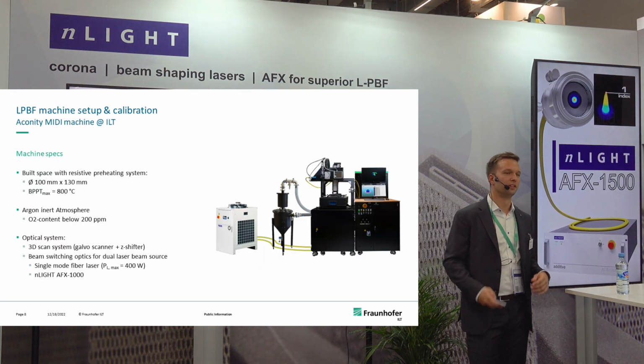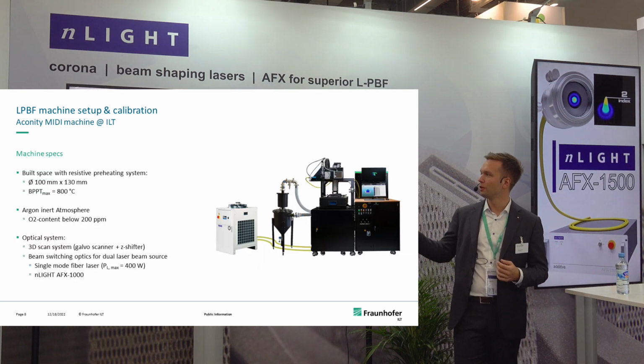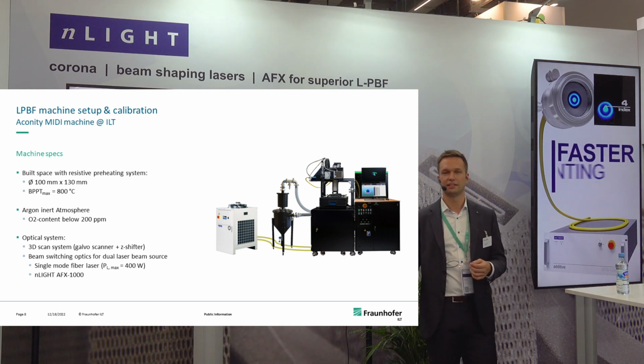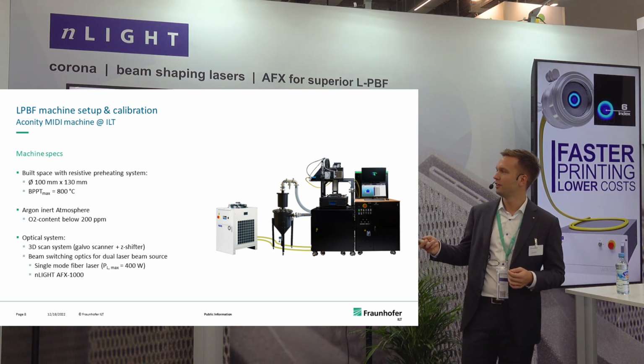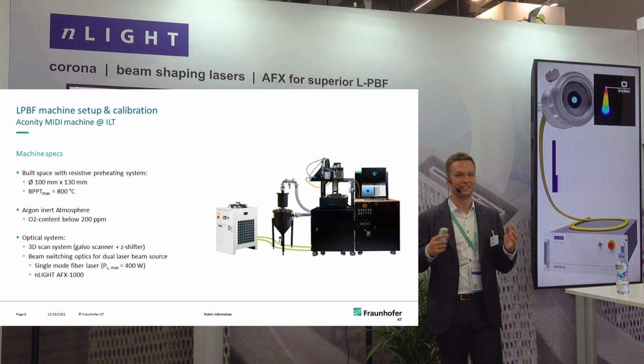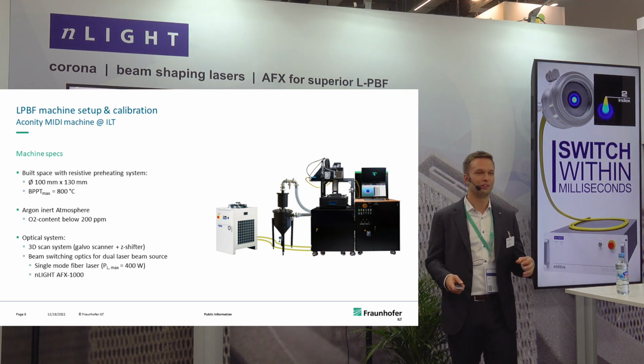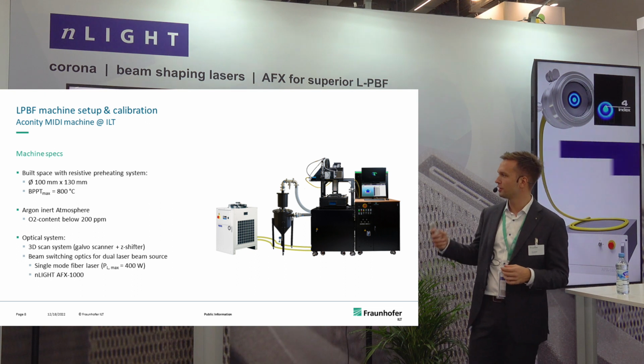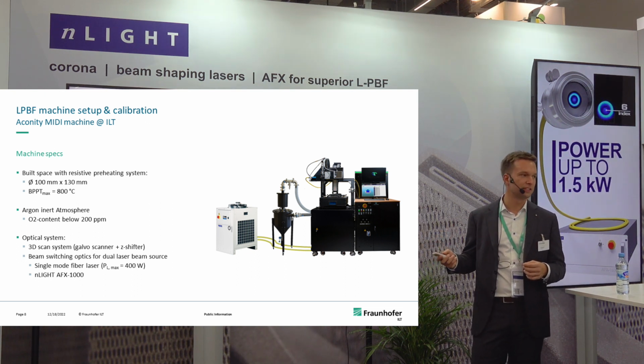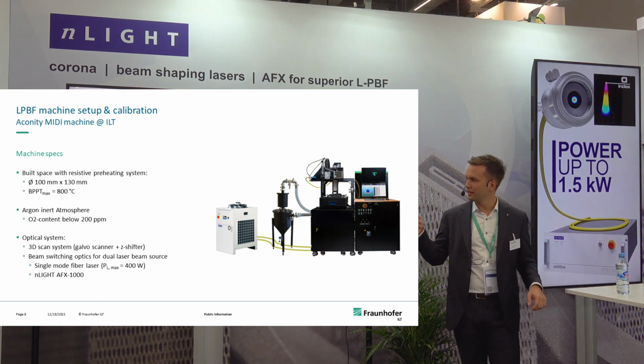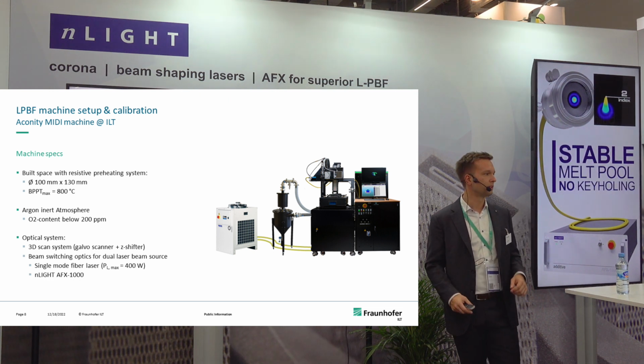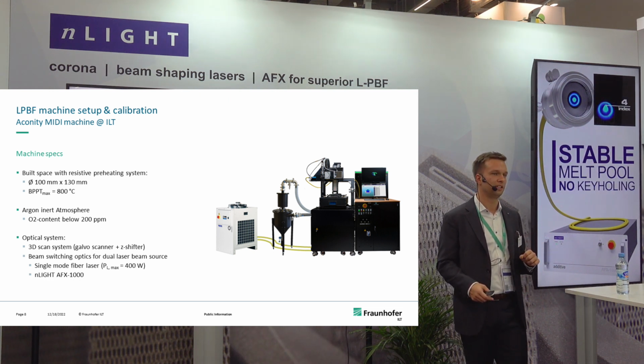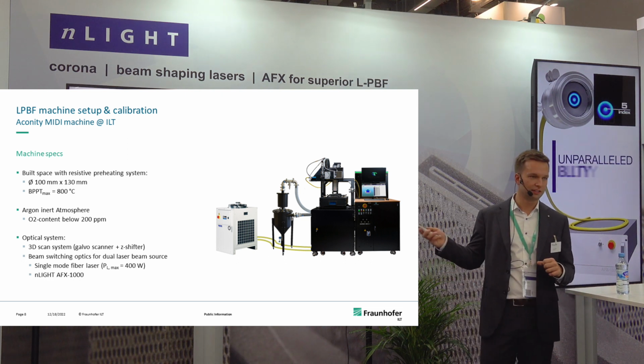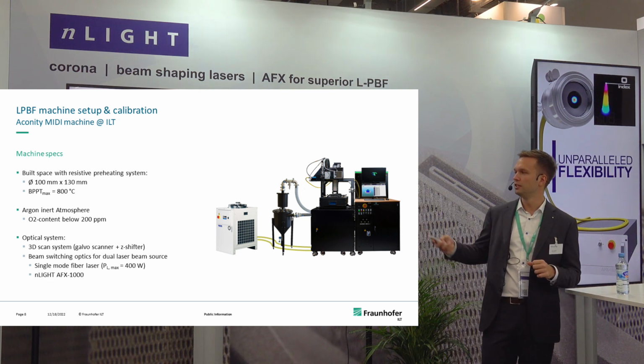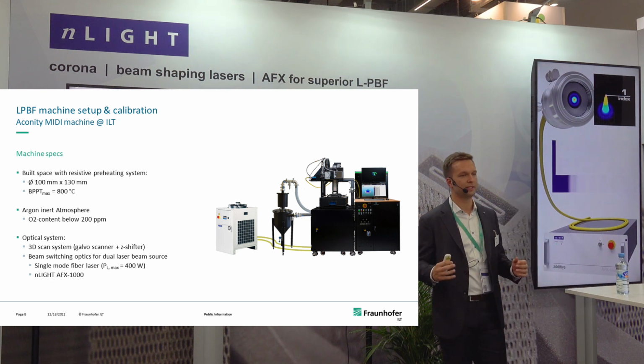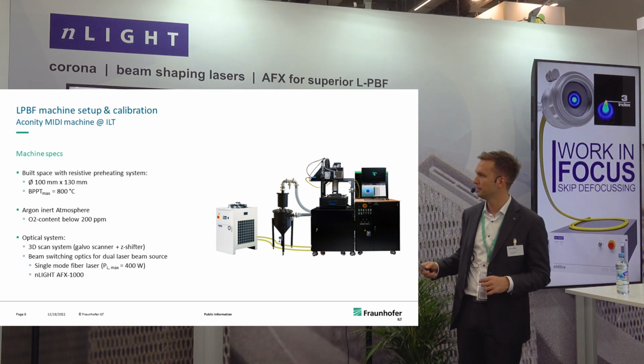What we did to address this topic is we used one of our lab systems. This is an Aconity machine, very flexible. You've seen it in the previous presentation. Very good to work with in the lab. What's special about this machine is on one hand that we can preheat the build plate up to 800 degrees C for these hard-to-weld materials, on a reduced build volume of a diameter of approximately 100 millimeters.